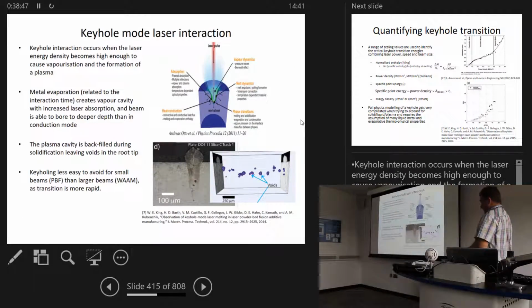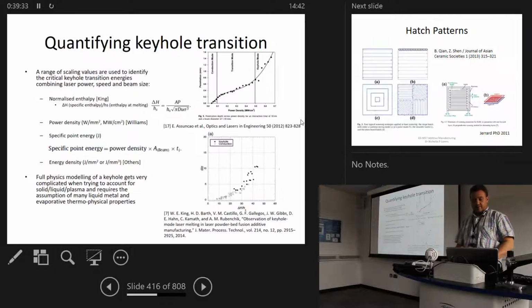So for powder bed, there's a very recent paper here from 2014 from Rain and King, and it typically gets shown just onto a single substrate with the powder, but what it does show is that it may lead to additional porosity. You basically overcook the material, and when that keyhole area refills after it solidifies, you potentially end up with additional porosity in that area, which then appears as a series of voids as you go down. Any occurrence of porosity is best avoided. They impinge on your mechanical properties, which is why a lot of work's going into this.